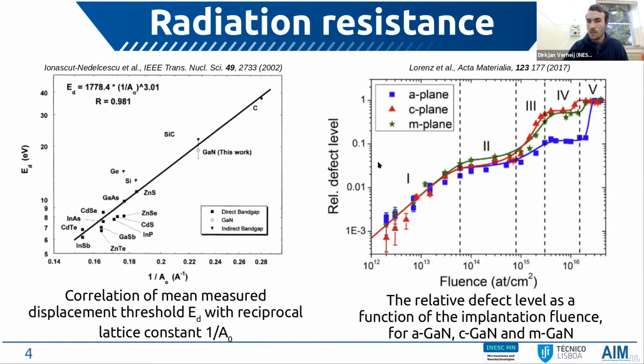But I want you to focus on the evolution of the relative defect level for fluences up to 10 to the power 15. As we can see here, the relative defect level starts to increase linearly for the lower fluences. But then at this point, in region 2, the relative defect level actually stabilizes. And this stabilization occurs because the density of defects is high enough for the defects to recombine with each other.